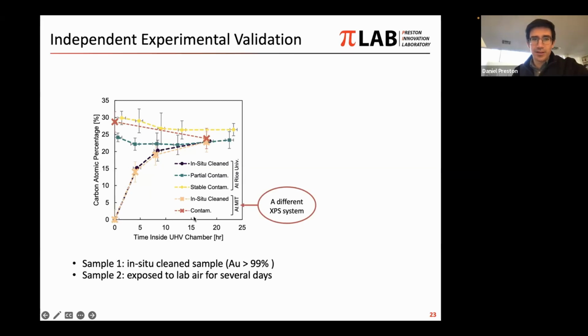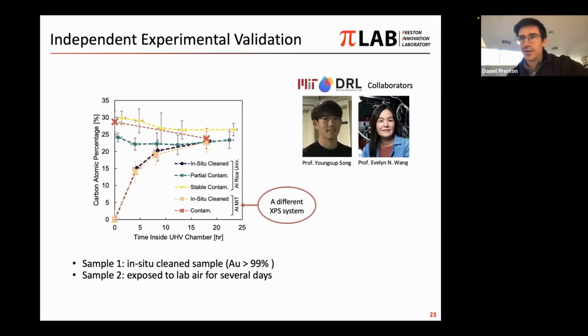And we also looked at an initially contaminated sample that had been sitting in the lab air for days, put inside of the XPS chamber at MIT, in these red-colored X markers, and found again a nice agreement with the results that we had already obtained at Rice. And in this case, the results here were obtained by Young-Sup Song, who's going to be starting his professorship at the University of Florida, I believe, pretty soon.